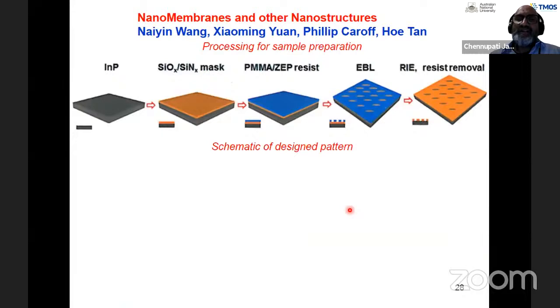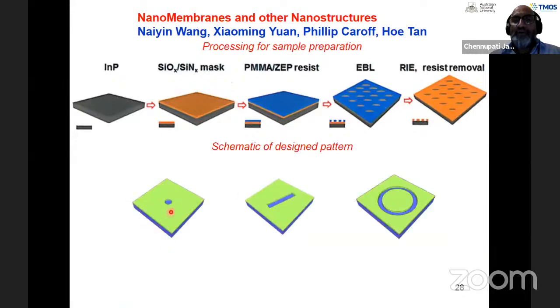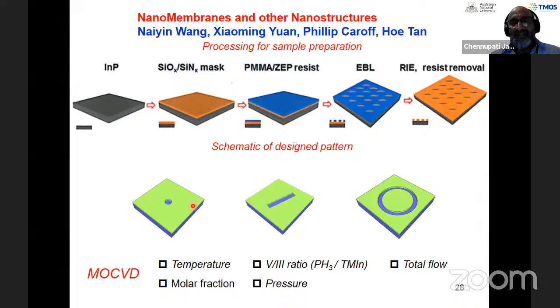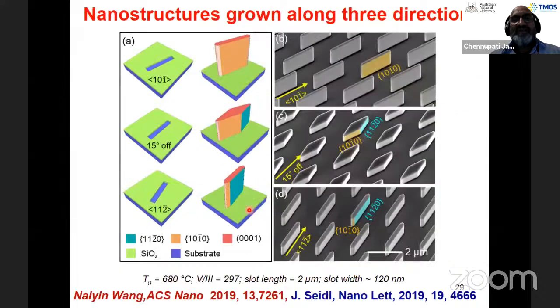So then we asked ourselves, instead of opening a hole, what will happen if you open a slot or a ring in these masks, the silicon dioxide mask, or open a hole in the middle, for example, or a slot or a ring. This is the work of Dr. Naiyin Wang, who just completed his PhD. Again, he spent about 4 years optimizing various growth conditions to be able to really grow these structures. So here's a case where Naiyin Wang opened a slot along a particular crystallographic orientation, 101 bar, and then he put it into the MOCVD reactor, heated it to 650 to 750 degrees Celsius, and introduced the gases needed for growth of indium phosphide.